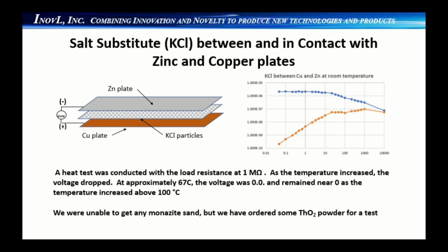For this test, we sprinkled KCl onto a copper electrode and placed a zinc electrode on top of the KCl. The plot at the right is the data from the load test conducted at room temperature.